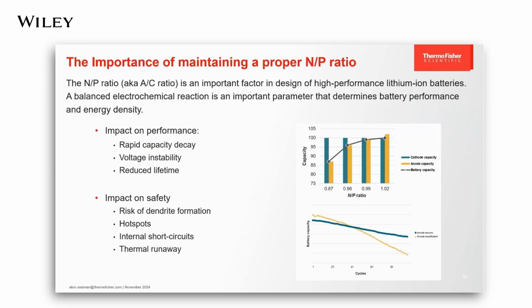Ensuring the uniformity of the active material loading during the electrode coating process is one of the most critical quality parameters. When the anode and the cathode come together in a battery cell, the ratio of anode to cathode capacity, A to C ratio or N to P ratio, will determine the electrochemical balance and will affect the performance of the cell. Anode to cathode balance needs to be maintained at each point over the entire area of the electrodes, not just on average.